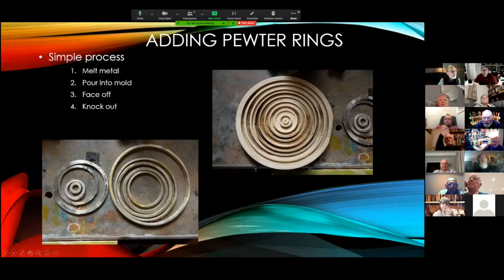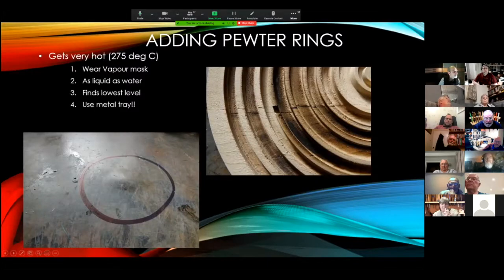I've used some pine molds, and they burn even faster. One of them actually started to smolder, so you have to be very careful. And molten metal flows like liquid, and in this case, it cracked the mold, and some of it spilt out onto my workbench, and you can see here that it melted. The workbench has got a Formica type top, so now I always use a metal tray to contain any spillage. So it's worth bearing in mind.